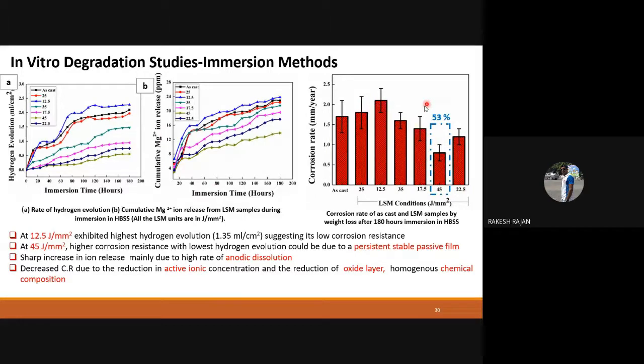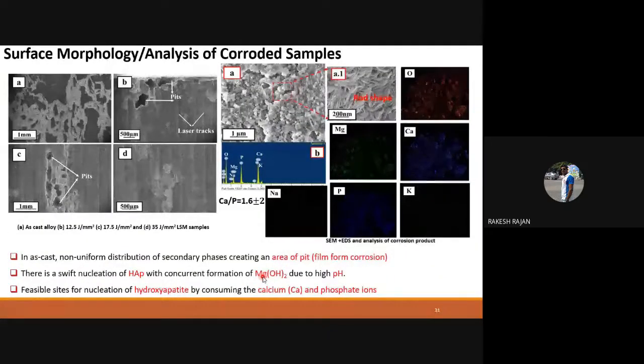So around 53% improvement in corrosion or degradation is observed after surface modification by laser melting. This is the surface morphology or analysis of corrosion as we investigated in previous slides. The same kind of product and surface has been observed here, and these are the mappings.